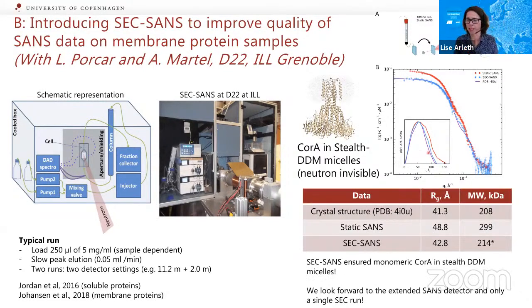And some of the numbers are illustrated down here, but what you can see is that the molar mass of the SEC-SANS produced samples is very close to the theoretical molar mass, whereas with the static SANS approach, we systematically obtain a too large molar mass, so we don't expect them to be monomeric in the form that we would like. And I would also emphasize that we are one of the groups that look very much forward to the extended SANS detector that is being planned at D22, so that we only have to do a single SEC run in order to cover a large Q range.